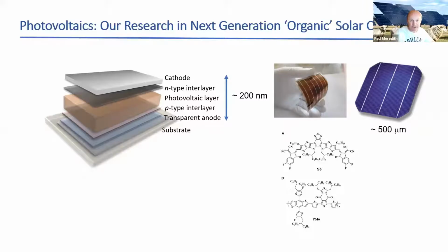However, they produce a photovoltaic effect in much thinner layers than either the 50 microns of the cadmium telluride panels or in fact the 500 microns of the silicon panel. And in fact, our solar cells are only about 200 nanometers thick, which of course is about 100 times thinner than the width of a human hair. So very thin layers indeed. They're extremely simple, very simple solar cells indeed. Basically, they're a layer that produces the photovoltaic effect made of these organic semiconductors glued between 2 electrodes, one of which is transparent to let the light in, and the other is a reflecting metallic electrode to extract the electrons and extract the counter holes and generate the photovoltaic effect.